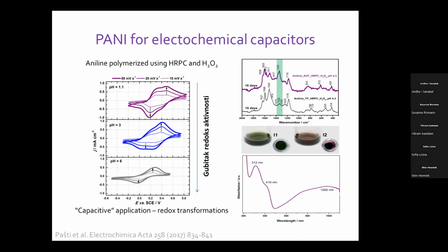aniline polymerization using horseradish peroxidase. It's not a very common approach to polymerize aniline, but it's really interesting because depending on what we have during the synthesis, we get really different properties of these materials. And in principle, if there are some template vesicles present in the solution, we can get either conductive or non-conductive polymers as a result. And what we were really happy about is that this conductive form of PANI that we got during the synthesis had really high capacitances.